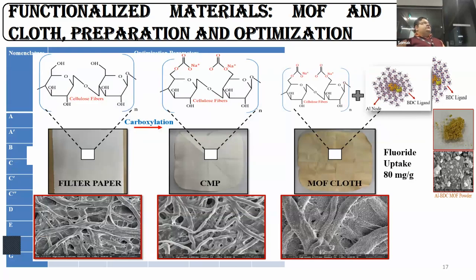So how did we do it? We used something known as carboxylation. Firstly, we used this filter paper and applied the carboxylation method, where we imported sites for anchorage, where this MOF can be imported onto the filter paper. Once we imported the MOF structures, as you can see from the same images, this MOF gets deposited on the surface. Instead of calling it the filter paper, we start calling it the MOF cloth. This entire thing we immobilized on the surface of the filter paper, and we started calling it the MOF cloth, which can be used for a sort of defluoridation application.